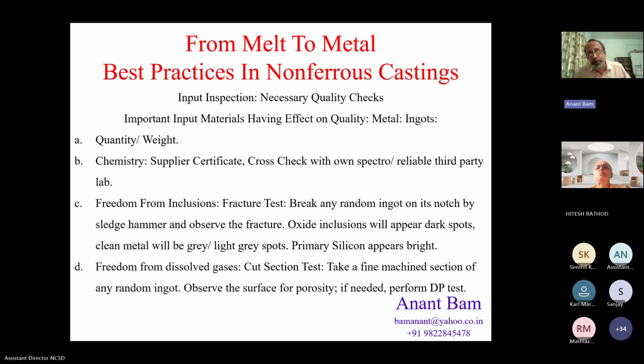When you find layers, you are not assured of the consistency of the material. Every layer may be from different materials. In between two layers, there can be anything which you don't want. So do not accept a layered ingot. Every ingot has to be a single piece entity. You have to break one ingot from every batch randomly at the notch with a sledgehammer and observe the fracture. I have photographs in coming slides. We will discuss that later.